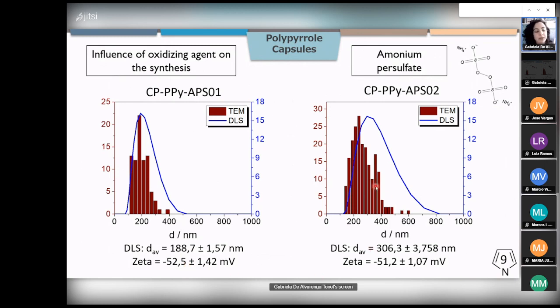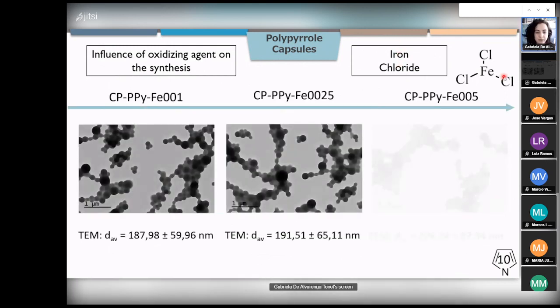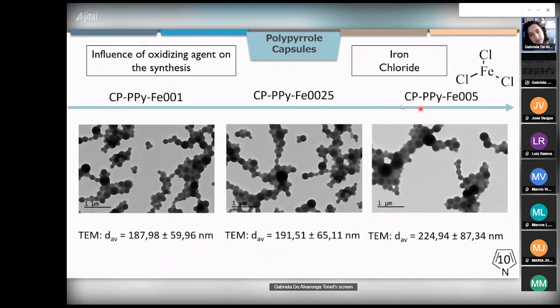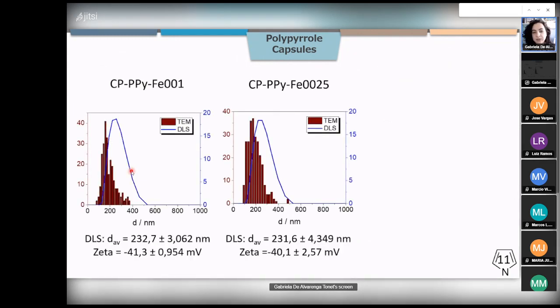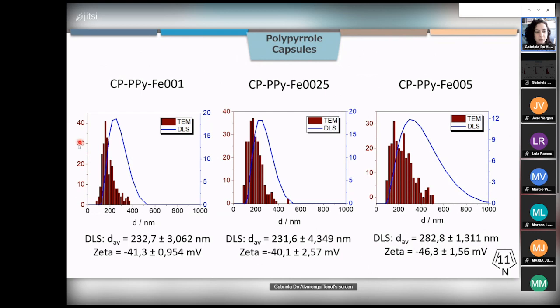And then we moved to use a different oxidizing agent, which is iron chloride, and we observed the same trend with 3 different concentrations. So the more concentrated the oxidizer, the bigger we get the capsule, so we are actually promoting formation of thicker shells of the capsules, but roughly they have all the same morphology and integrity. Again, the results of measurements of TEM and DLS were in agreement, and we also observed that for this different oxidizer, we still have the incorporation of the SDBS, as we can confirm from the zeta potential measurements.